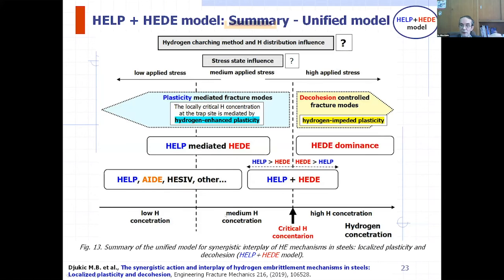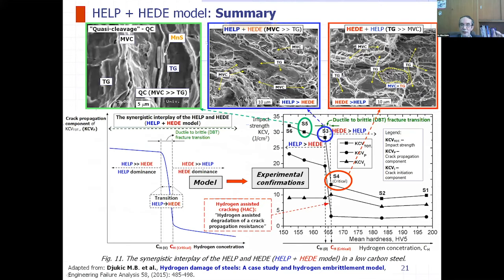But also for the same material at a lower or medium hydrogen concentration and low applied stress, we could have an opposite effect, softening due to hydrogen-enhanced plasticity and plasticity-mediated fracture process, which is not related to the cohesion mechanism, which is the typical fracture mode, as we can see on bolts, like fully transgranular, intergranular brittle fracture. So we can have a combination, as you can see here, of something like quasi-cleavage features, which is still undefined because it is connected with the remaining plasticity of material. As you can see, we have a microvoid coalescence area, but also we have a transgranular and initiation of an intergranular area. So in this case, we could have a softening of material due to enhanced plasticity due to hydrogen.